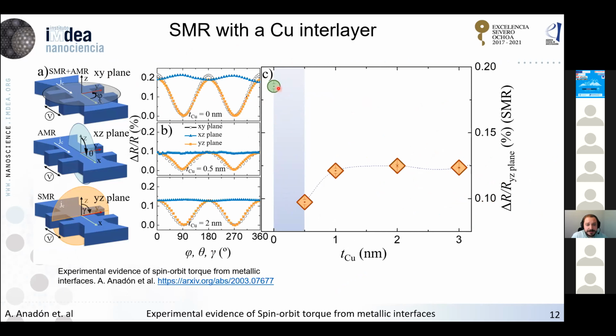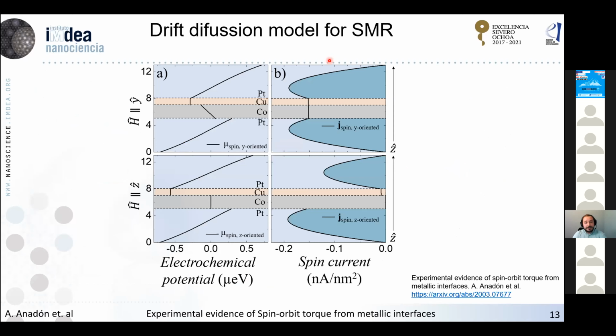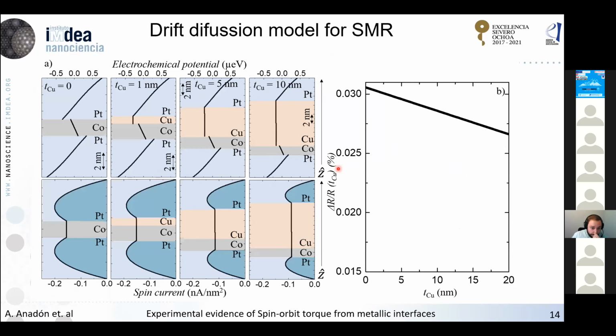Basically, this drastic reduction of the spin-Hall magnetoresistance is most likely going to be because of spin memory loss. And to understand this, what we did was we developed a drift diffusion model, and we can see here the high resistance, and a small resistance when the field is perpendicular, in the Y and Z direction. So what we did was we studied how the spin-Hall magnetoresistance depends first on the copper thickness.